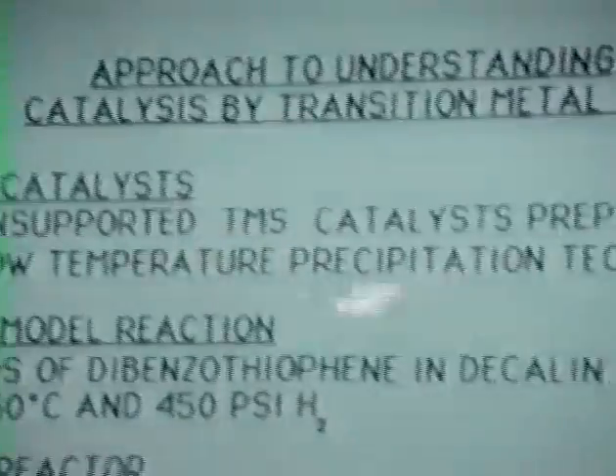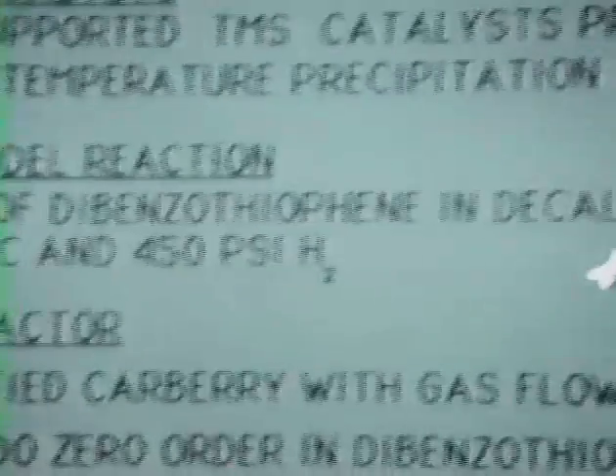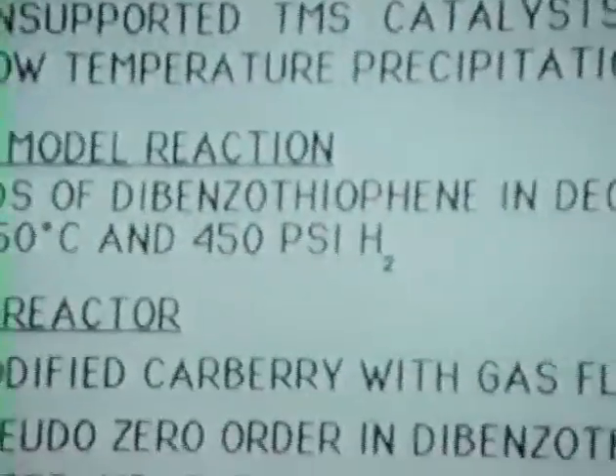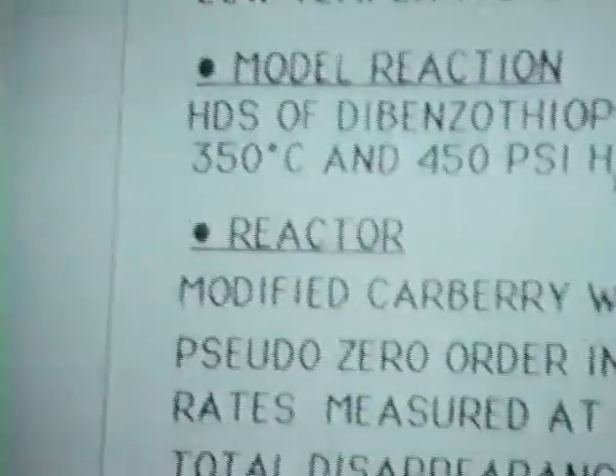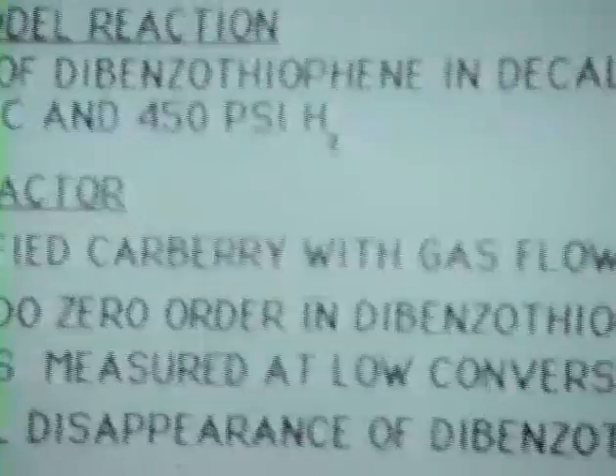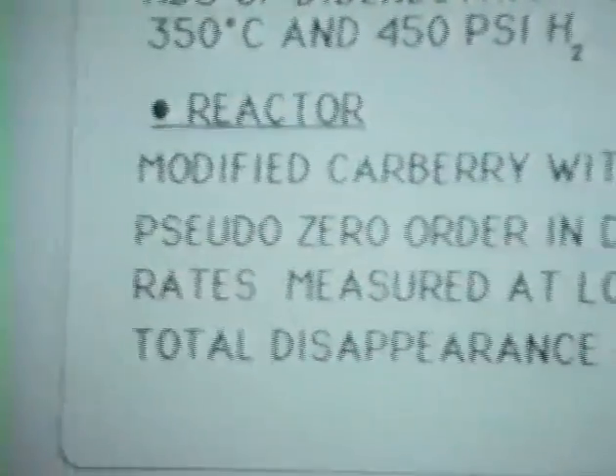Now, in this interdisciplinary approach, what I would like to talk about initially is some unsupported transition metal sulfide catalysts prepared by techniques that are in the literature, like low temperature precipitation technique, with a model reaction, HDS of dibenzothiophene and decalin at 350 degrees C and 450 psi. We have found over the years that this is very representative of molecules in real feeds. If you can do the desulfurization on this molecule under these conditions, you'll get a pretty good measure of what you can do in a real feed, within certain limitations.